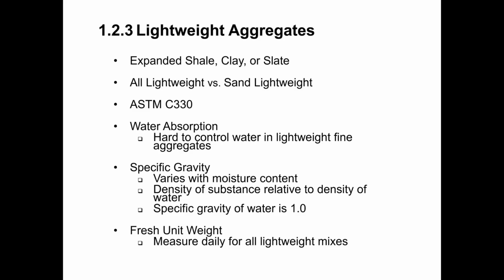These lightweight aggregates are difficult to work with. They do complicate the manufacturing and the quality control process. So we can use a lightweight coarse aggregate and still get a significant reduction in the unit weight of our concrete mix, but use a normal weight sand. Using a lightweight sand is even more complicated than using a lightweight coarse aggregate. And so just to minimize the complexity and the difficulty, a lot of plants elect to use a regular weight sand and then a lightweight coarse aggregate if they need to develop a lightweight concrete mix.